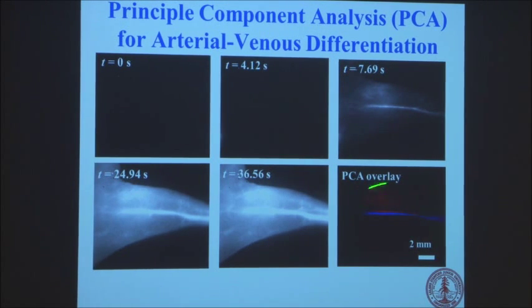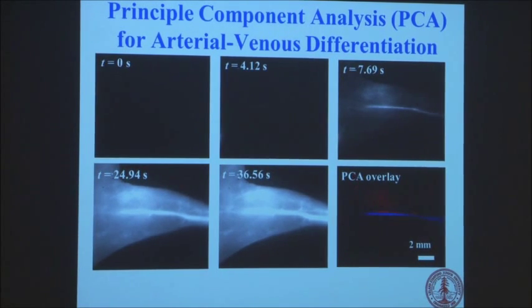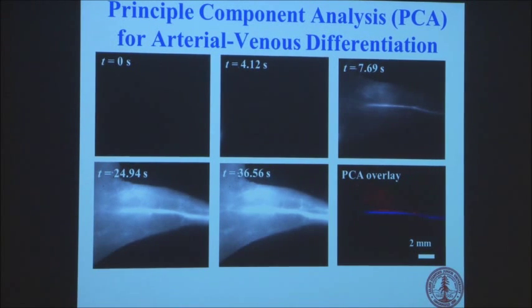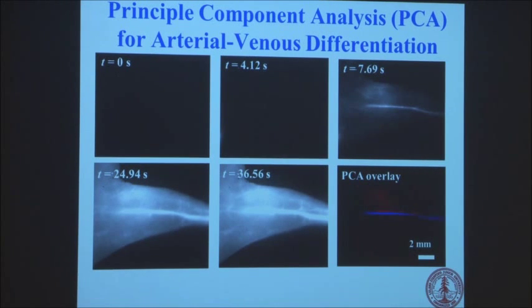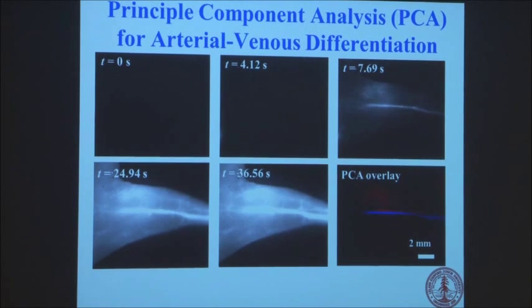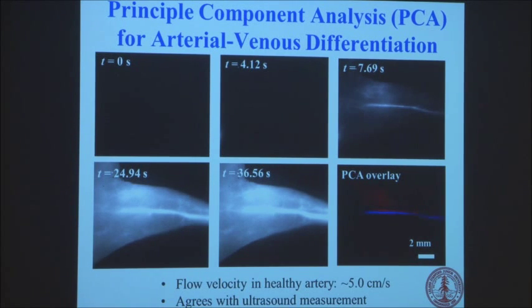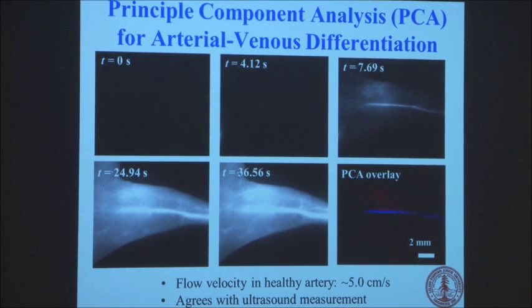And the last image here is this PCA again, this principal component analysis. And in this case, we found something interesting: you see two colors, two components. So one of them is actually an artery, and the other one is a vein. Okay, so in other words, even though they are too close together to be resolved very well from this kind of image, because of the different dynamics of blood flow in these two types of vessels, you can actually find out there's a vein next to an artery, okay, by doing this analysis. So the flow velocity you can measure is about 5 centimeters per second.